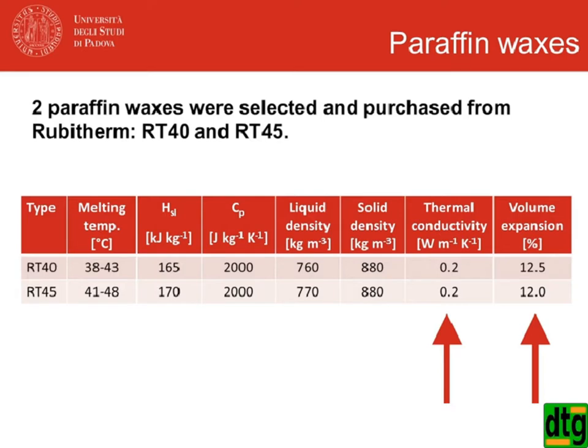So what about paraffin waxes? Here you have a table. These are paraffin from the market, RT40, RT45. The thermal conductivity is rather low, 0.2 watt per meter Kelvin. The volume expansion is, in this case, 12%, but it can reach up to 50%.